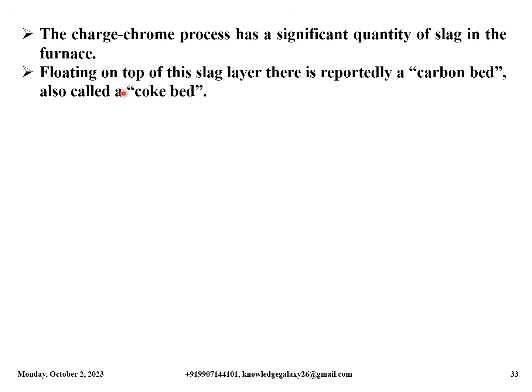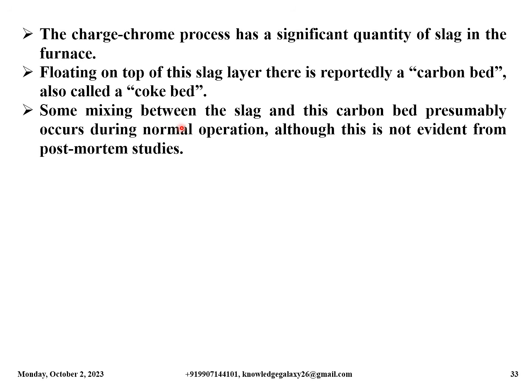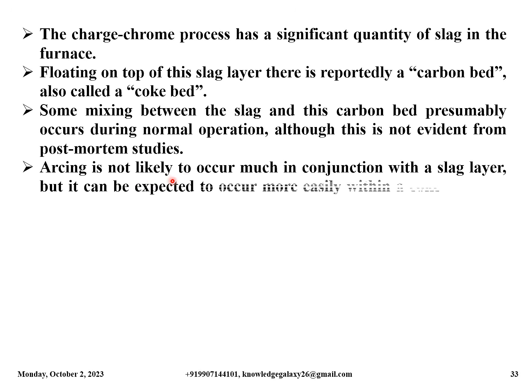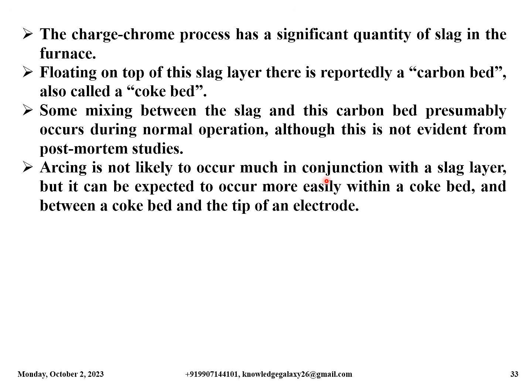The charge chrome process has a significant quantity of slag in the furnace. Floating on top of this slag layer, there is reportedly a carbon bed, which is also called a coke bed. Some mixing between the slag and this carbon bed presumably occurs during normal operation, although this is not evident from post-mortem studies. Arcing is not likely to occur much in conjunction with a slag layer, but it can be expected to occur more easily within a coke bed and between a coke bed and the tip of an electrode.